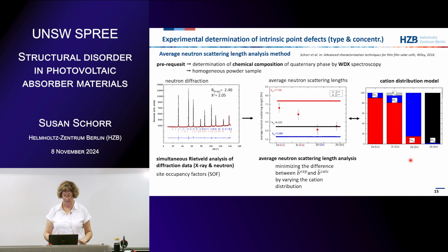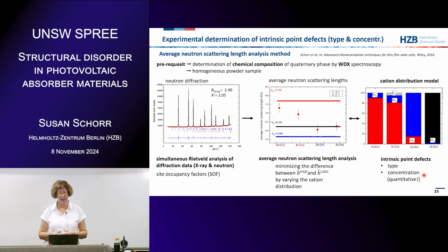So now when the experimental and the calculated values agree, then we say, okay, this is our cation distribution. And from that we now know which type of defect we have. And because we also have the lattice parameters, we can also calculate the concentration for each defect per cubic centimeter. So it means we have a qualitative and a quantitative result from that.